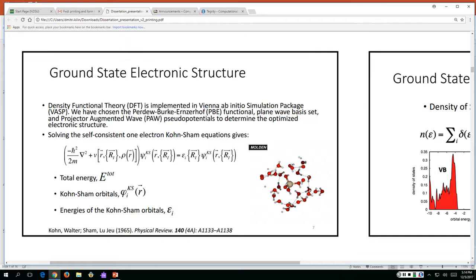So it's skipping that extra state contributed to the top of the valence band. For the closed systems, again, you see large peaks at the subgap energies that are shown, and also for the band gap. And then for the singlet state, where there's no additional electronic states added in, there's just a large single peak at the HOMO-LUMO gap.